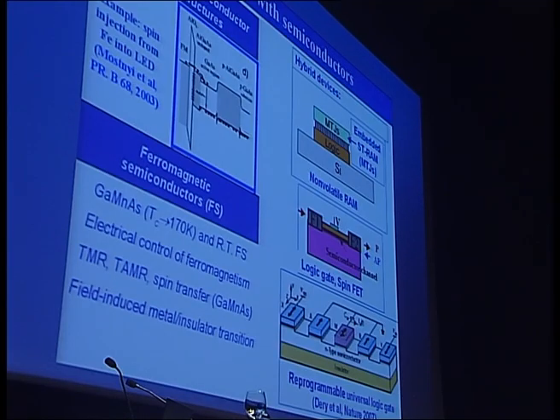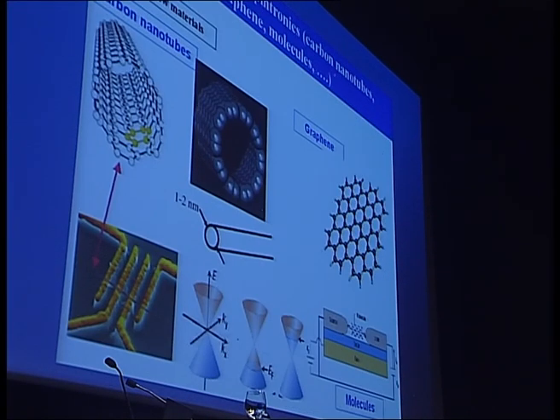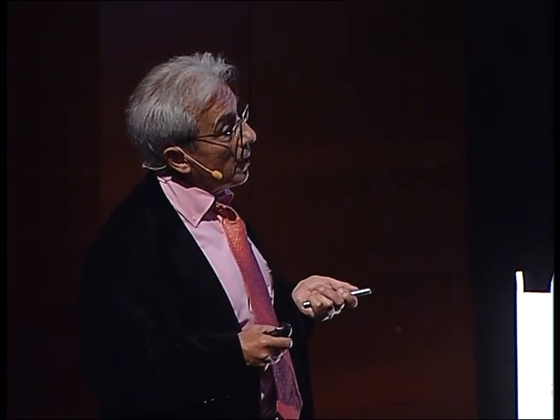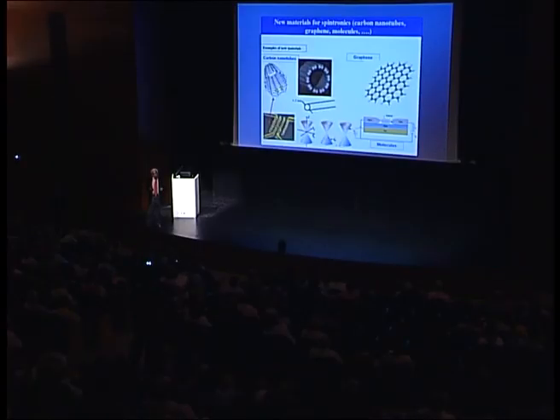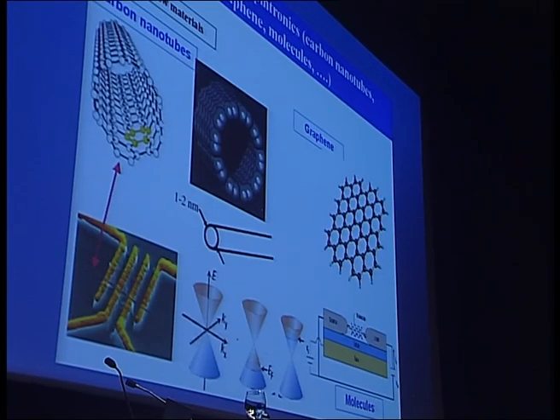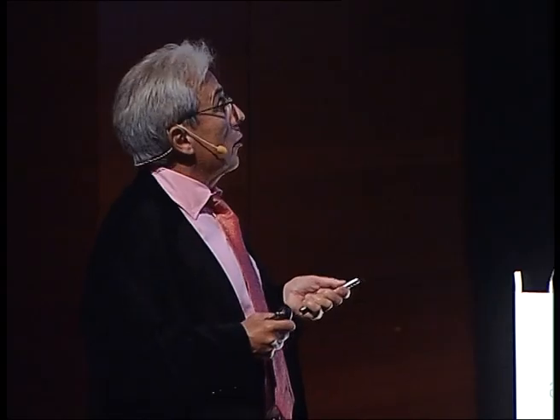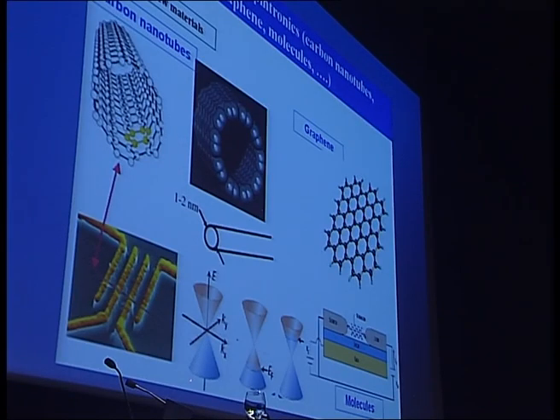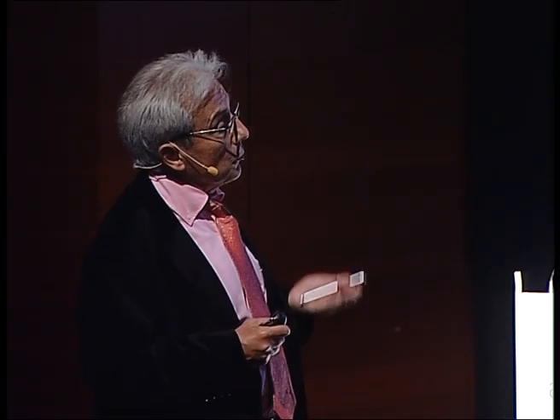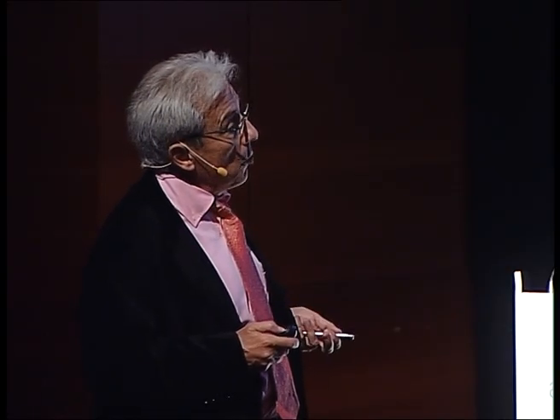On the contrary, in my opinion, much more promising materials are carbon-based materials. In fact, nanotubes, graphene, and several types of molecules. Why? First, due to the small spin-orbit coupling of carbon, the spin lifetime is expected to be sometimes very long. And secondly, the velocity is very high. This is interesting for the dwell time. The electron can propagate from, for example, source to drain very rapidly. And this velocity, due to the unique dispersion relation, the linear dispersion of these materials, like graphene or carbon nanotube, is high even for small carrier concentration. So these materials are very promising for most of the spintronic applications.